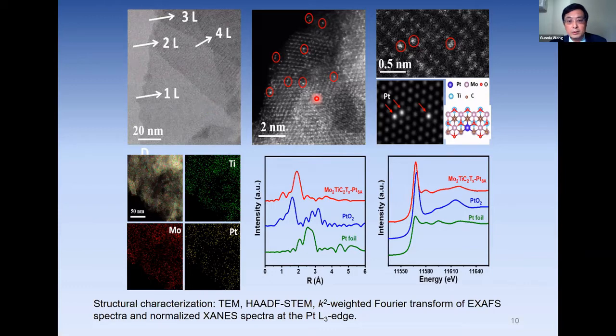And also when you observe by HAADF-STEM, you can identify Pt, platinum single atoms have been successfully immobilized on the surface of the MXene. And furthermore, we use synchrotron EXAFS and XANES. We confirmed the platinum single atoms are positively charged. That means we successfully prepared the Pt single atoms on the surface of MXenes.